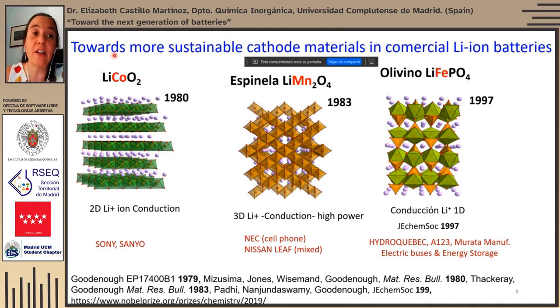So instead of using cobalt, which is mined mostly in Congo and not in very humanitarian conditions, let's say, other materials composed of manganese or iron as the transition metal, which are much more abundant and sustainable, have been developed. The lithium manganese spinel was developed as well in Professor Goodenough's laboratory at Oxford, with his postdoc Mike Thackeray.